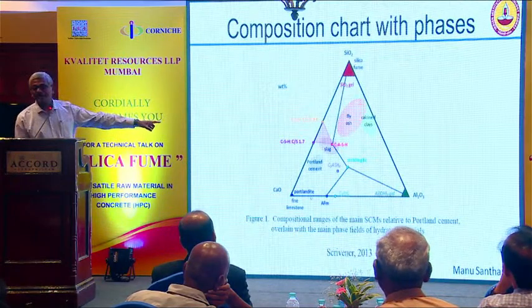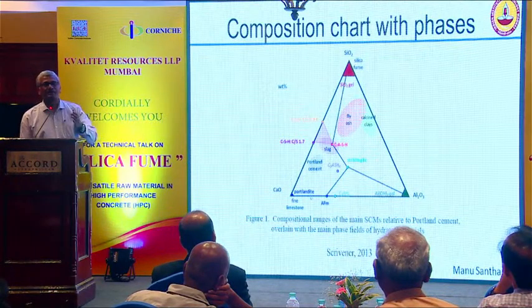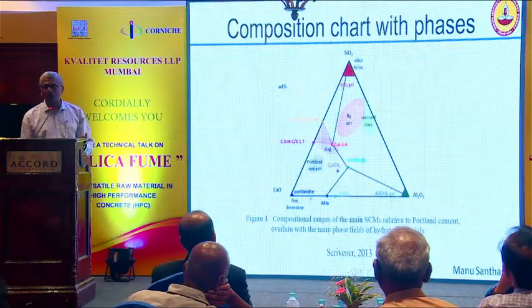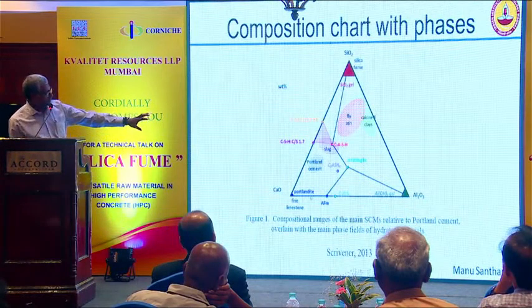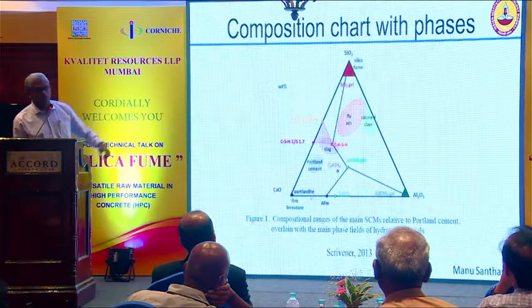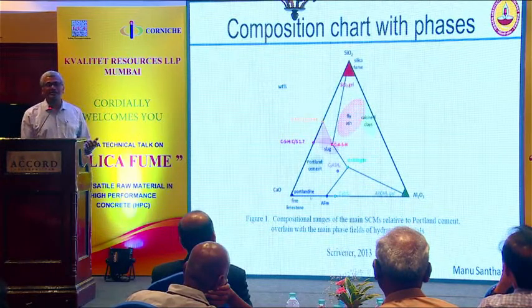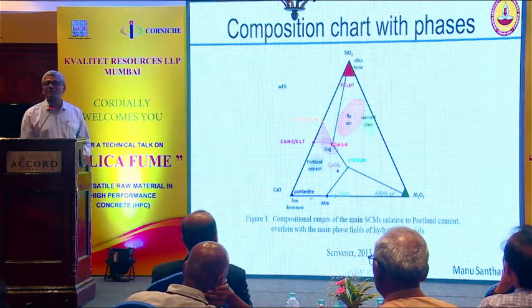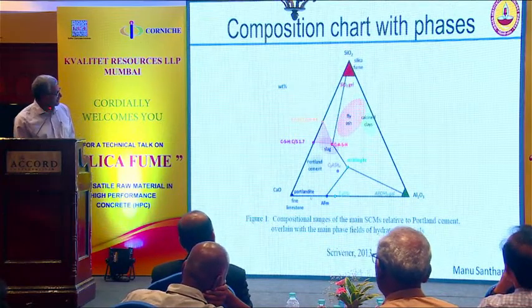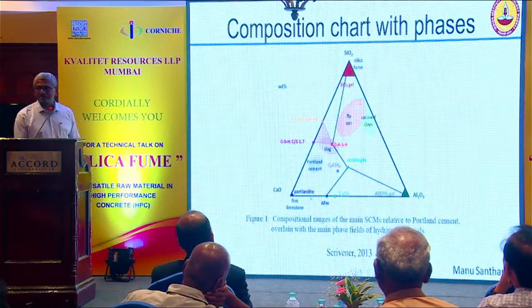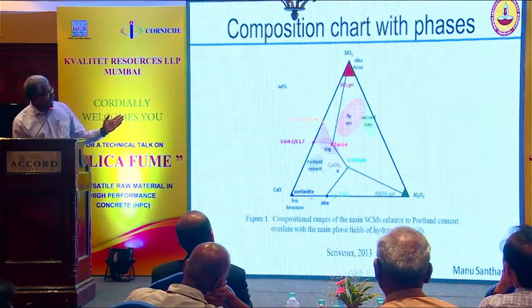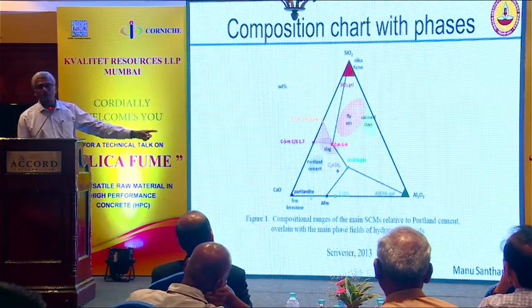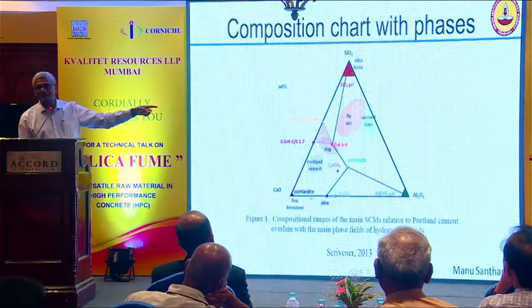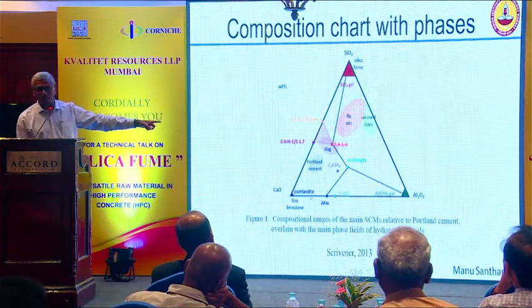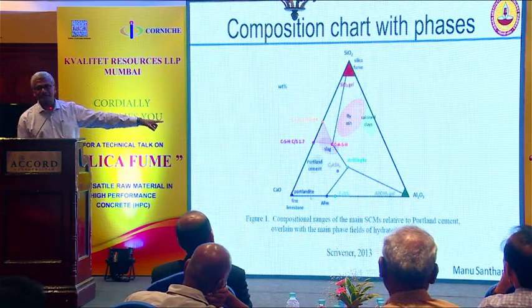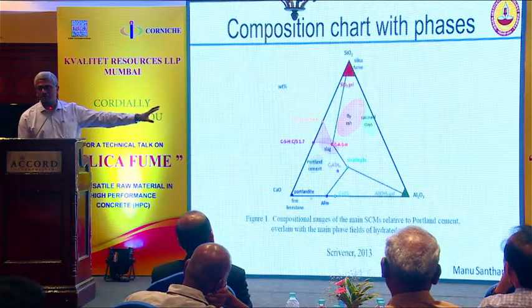If you go to slag, which has got calcium, it's got alumina, it's got silica, all of those things are there, you'll start forming phases that are towards the center, like your CASH. Nice name, cash, but it's calcium aluminum silicate hydrate, right? You can also form some crystalline phases like stratlingite. When you're going towards calcined clay, which is aluminosilicate, that has to then combine with your calcium to again form your products like CASH and stratlingite. Fly ash will also be somewhere there.